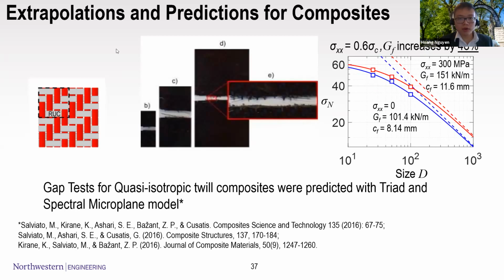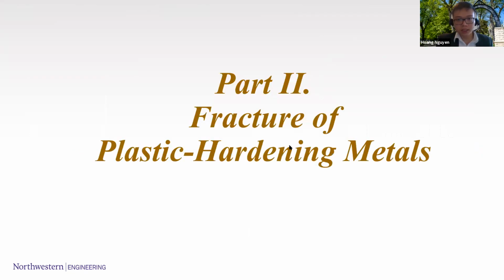The final prediction for the quasibrittle material is for composite. So we applied the same testing configuration for composite, applied at a certain 60% of the compressive strength of a composite, and we can see an increase of 40%. And I want to note that this composite is a quasi-isotropic type of composite, which means that you have the fibers running in all directions, in this case 0, 90, 45 and minus 45 degrees. So that is the fracture of the quasibrittle material, and we see a very strong effect of the sigma xx on the GF. So how about the more ductile materials like metal?